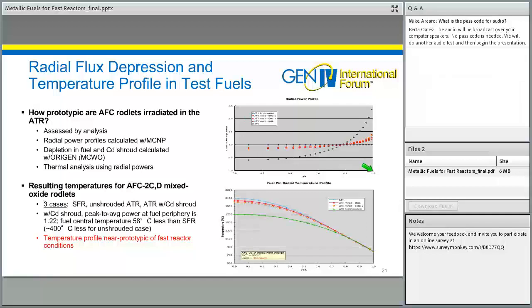And if we just put our test fuels into an unaltered thermal spectrum, you would see massive peaking of the power at the fuel periphery and serious depression of the power in the fuel center. And what that would do to you temperature-wise would be something not very good. And so this is a temperature plot, fuel temperature versus radial position of the fuel. And I've done this plot for one of our oxide fuel tests just because the effects are exaggerated in oxide fuel, which has a very low thermal conductivity, but a similar effect is achieved in metallic fuel.